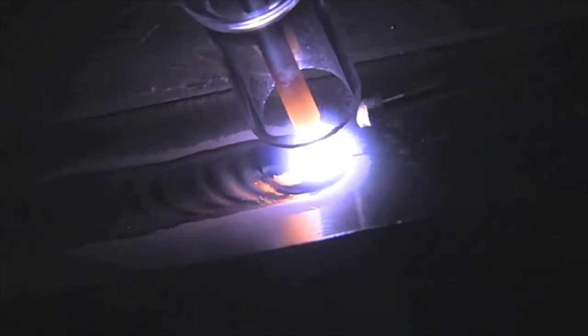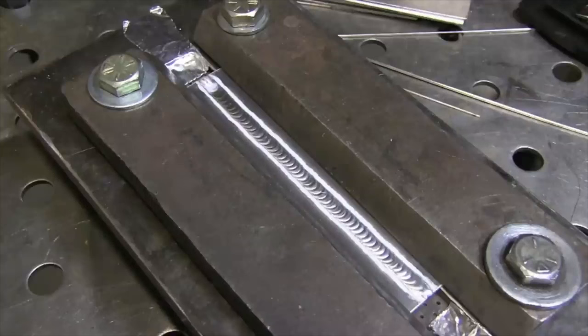Now for thinner materials like 063 or something, you don't really have to worry about any kind of a preheat. But using chill bars does help in minimizing the heat affected zone and minimizing the area where strength is lost. Some loss of strength is inevitable when you weld aluminum. Now, the first thing you need to know about welding aluminum is there are some aluminums that are not made for welding. The main two that you'll hear about are 2024 and 7075. There's a few others, but those are the most common, mostly used in aviation. And like if you're looking at a big jet, most of what you're seeing is not weldable.